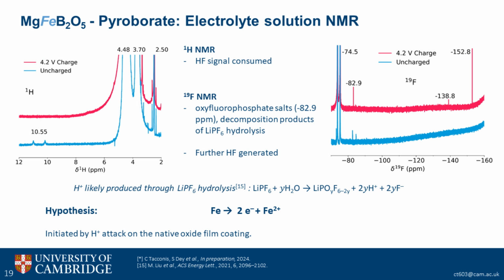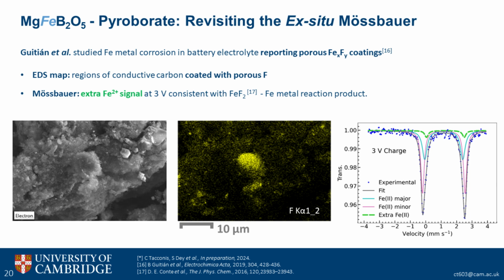LiPF6 hydrolysis produces further HF. So what we know is we have HF in the electrolyte that's being consumed, and we have reason to believe that we're making even more HF, but we don't see it at the end of charge, so it's being consumed in the first part of the charge. And the hypothesis would be that this redox reaction of the iron metal is initiated by the proton attack from the HF on the native oxide film coating. So Jelena mentioned that metals have native oxide coatings. Our iron particles sitting in the electrolyte probably do as well. And we started looking at some other studies that reported iron metal studies of current collectors in electrolytes.